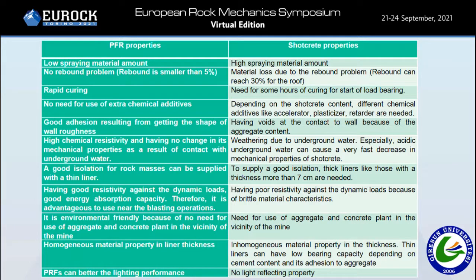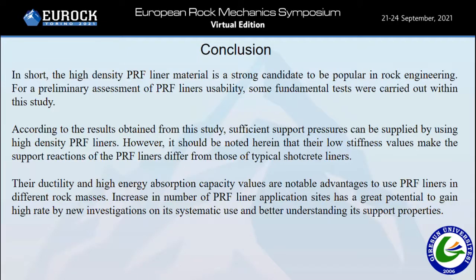A rigid polyurethane foam product was tested in the study. For higher support pressures, a different pair of materials with higher densities than that of the product used in the study is open to be tested for suggesting a better liner material. According to the results obtained from the study, sufficient support pressures can be supplied by using high-density PRF liners. However, it should be again noted that their low stiffness values make the support reactions of the PRF liners differ from those of the typical shotcrete liners.